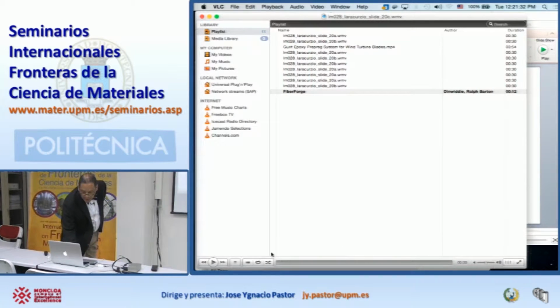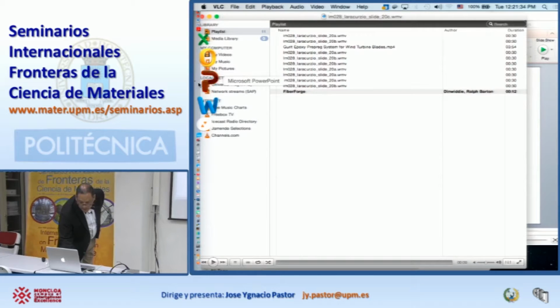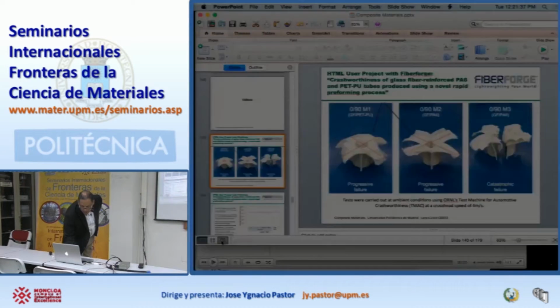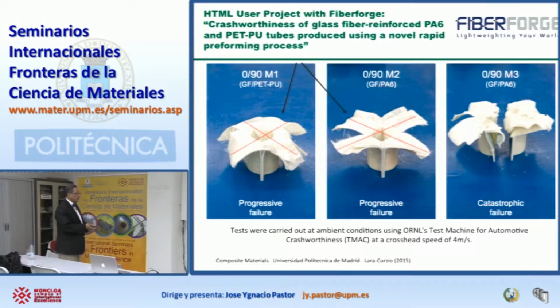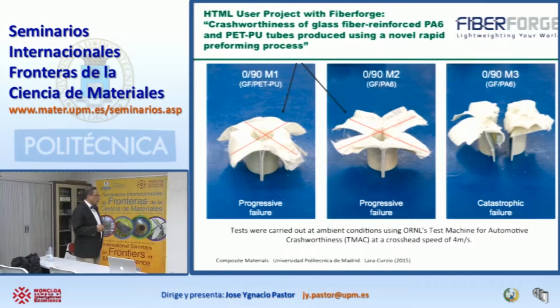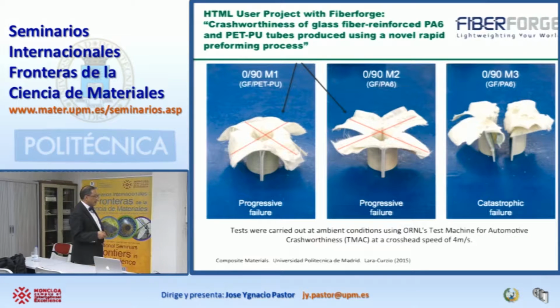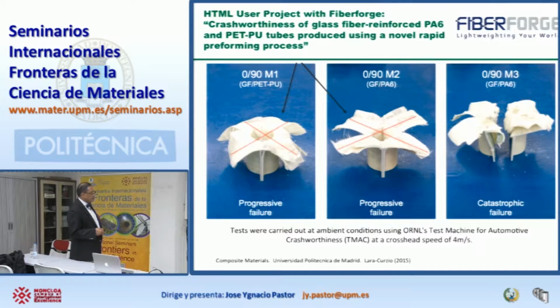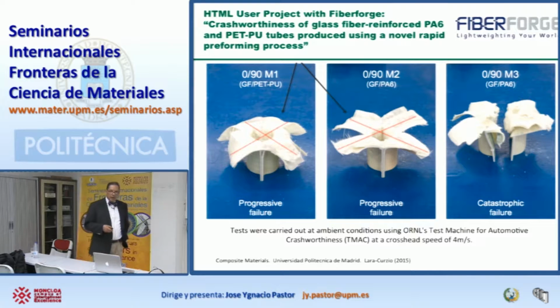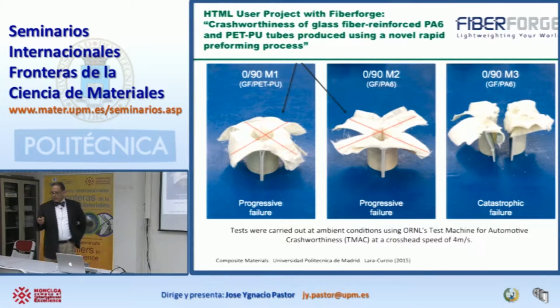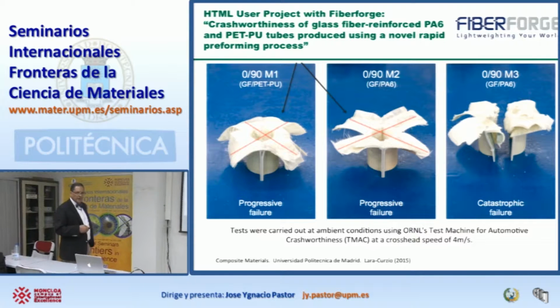So what we got from those experiments was that these systems had very different modes of failure. And in some cases, you have catastrophic failure where the two halves of the tube open up, like in this case. And then you have other cases where these halves remain bonded all the way to the end. These cases where you have partial opening, you can see how the composite opens up. And by using infrared camera, we were able to quantify how much energy in terms of heat was generated as part of this deformation process.